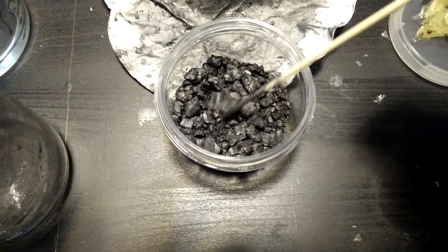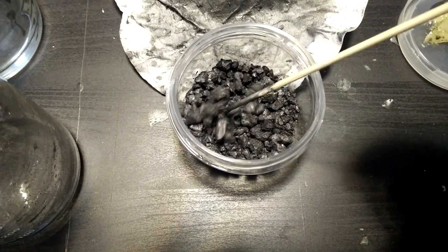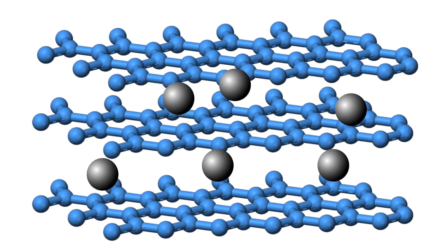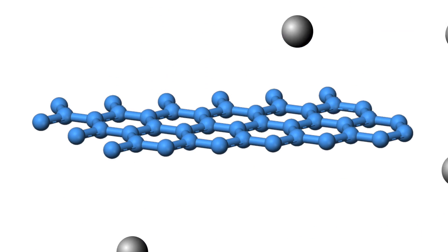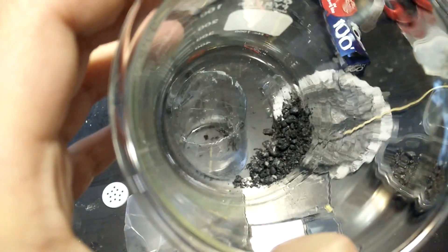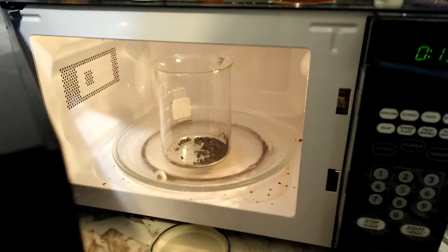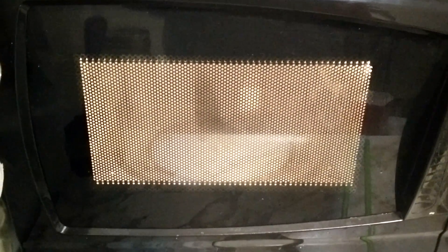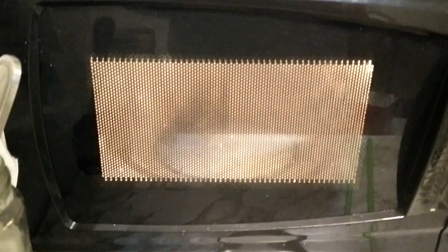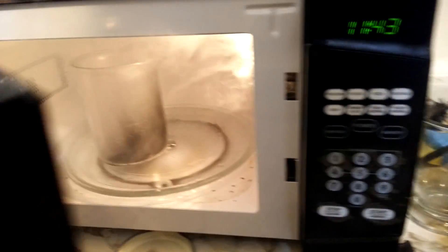So what can you do with this? In the graphene video, I mentioned that if you apply energy to an intercalated graphite, the ions force the layers apart. I've put a very small amount of the material in a beaker and put that into the microwave for a few seconds. As soon as the microwave starts, the graphite instantly starts sparking wildly. As the layers are ripped apart, the sulfuric acid is escaping and pieces of graphene are being flung all over the beaker. Because the sulfuric acid is being released, this produces a lot of fumes, so it's best to do this in a fume hood or outside.